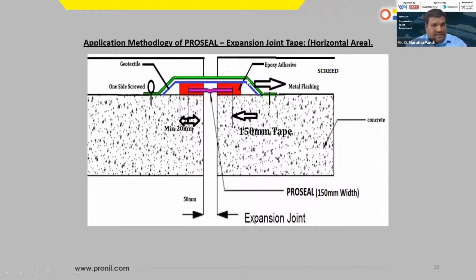I'm going to put one-sided screwed metal flashing of 1.5 mm, 2 mm thickness, or even 5 mm. Some of them will be putting it. So one side flashing screwing is required to accommodate the movement capacity. Then over that, the same groove or a small groove has to be allowed so that the expansion contraction should come up to the top level, to avoid cracks. A screed has to be laid on the top and sides of the metal flashing. Okay, I think this will give a better solution for the expansion joints in the podium slab.